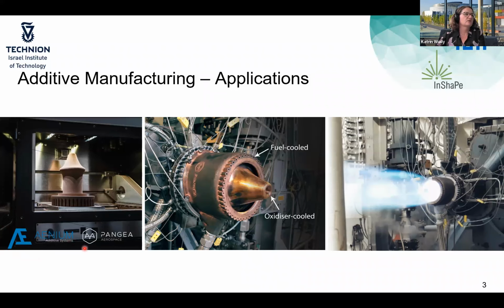And they are actually working together with a rocket manufacturer, Pangea, who tries to design a new rocket system, which is shown here on the picture. And actually that part, this one, and that part in the middle was produced with additive manufacturing with powder bed fusion technology. And the challenge there was that the material is a copper alloy, and to manufacture this copper alloy is quite challenging. So the idea for the use case partner within our project is that we can manufacture these challenging copper materials quite well and in a reproducible way, and we would like to reduce, for example, the costs for the product at the end and increase the production speed.